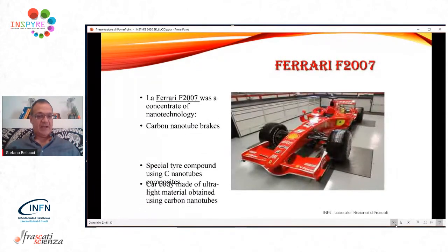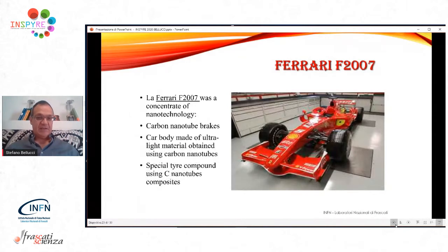Well, I give you here immediately an application that is as old as 2007, the Ferrari F2007, that actually with Raikkonen won the Formula One championship that year, was a concentrate of nanotech, from brakes that contain carbon nanotubes to the car body made of ultralight material that is a composite where carbon nanotubes are in a small percentage inserted as a filler, and finally special tire compound that uses carbon nanotubes inside the elastomer that makes the matrix of the composite. Now here, what properties are we using? Well, in the brakes and in the compound, we are using the thermal properties, because these thermal properties are responsible for the high performance of brakes that need to dissipate heat very, very fast, and the same happens during the braking phase, and the compound, the same.